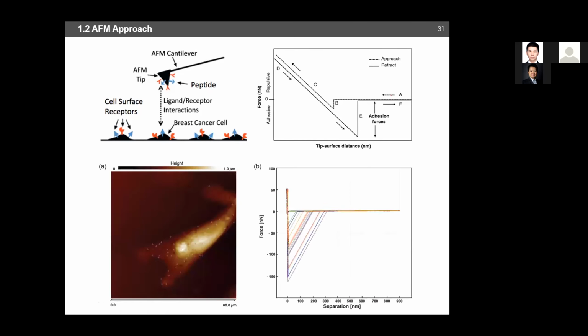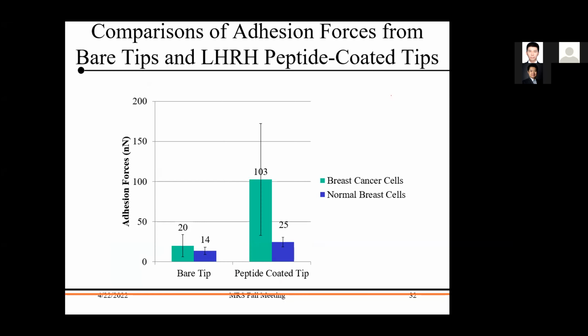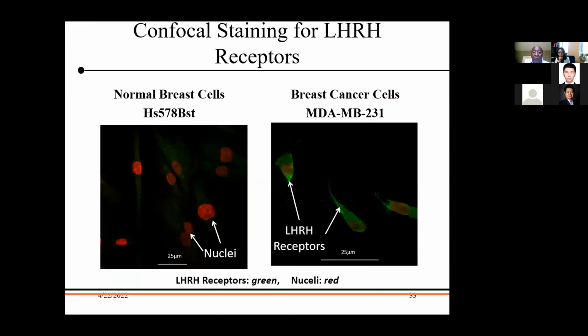So with experiments like this, and these have been repeated multiple times, one can now measure the adhesion associated with luteinizing hormone-releasing hormone peptide-coated tips, and show that these adhesive forces are much greater than those that you get in the absence for normal cells. So this gives us a sense that this works at the cellular level.